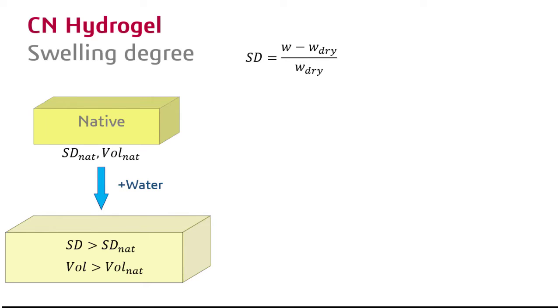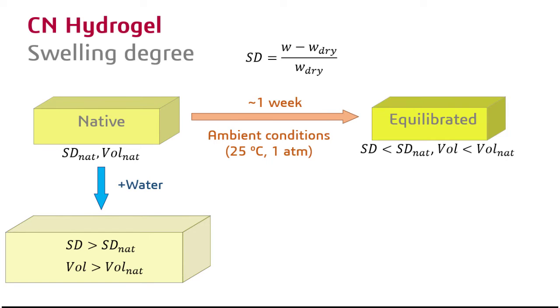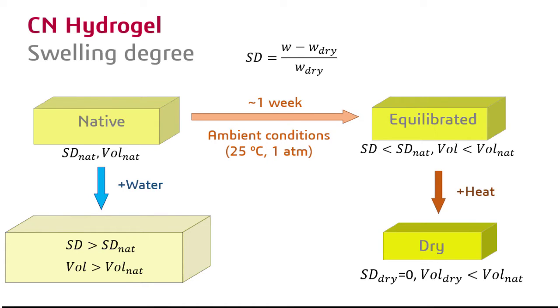However, if we leave the initial native sample under ambient conditions for 1 week, it loses water by evaporation, and we obtain a hydrogel that we call equilibrated. This means that the water inside its structure is in equilibrium with the environment, so the hydrogel keeps its weight constant. To obtain a dry sample, an external heat should be applied. We analyzed the self-healing capabilities of our CN hydrogel in each of these states, obtaining great results in the equilibrated state. This study was performed following these steps.